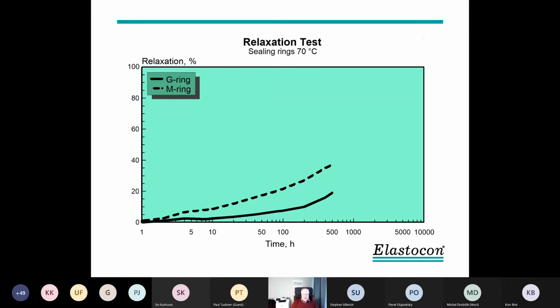Here I come to the graph we made from that test at the Testing Institute, where we tested for 1 year. We did a lot of tests on sealing rings for water pipes, which is still quite a lot of interest in that area. And we tested 2 rings from 2 different manufacturers at 70 Celsius. And after some 100 hours, we could see that one seems to be much better than the other.